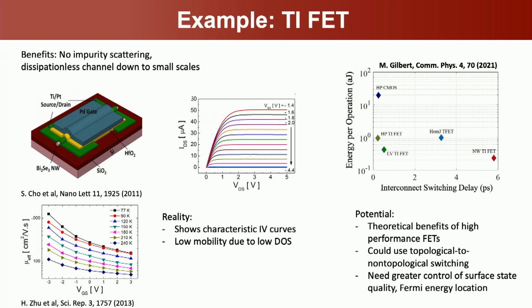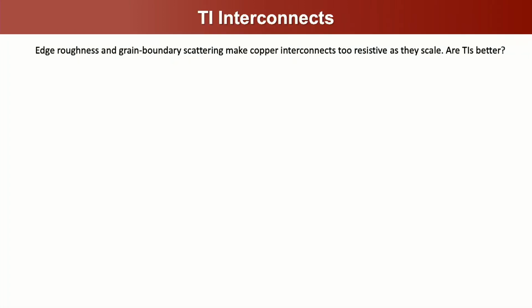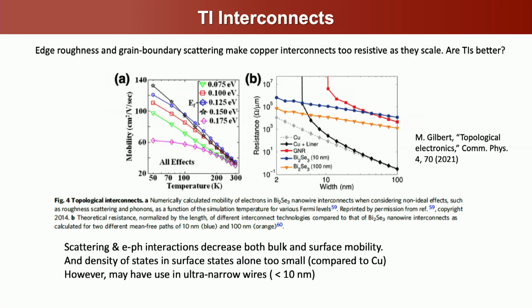The other application I wanted to mention is interconnects, because whenever I show that little wire with the high conductance, I always say, this could be good for an interconnect, and then I just move on from there. So I thought for you guys I'd actually show what an interconnect would look like in this case, because, as you can see, edge roughness and grain boundary scattering in copper make them too resistive as they scale, so you can ask, are TIs any better for this? And the answer is yes and no.